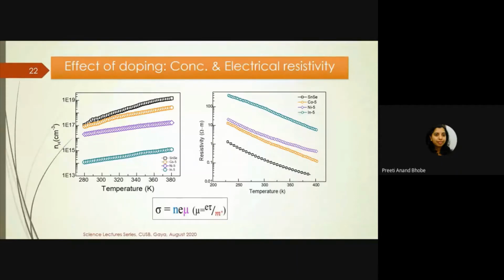What we find from the Hall effect studies is that the carrier concentration is getting affected to a large extent. In the case of the indium sample, you see the carrier concentration is really low compared to the black curve here, which is SnSe. Whereas with cobalt and nickel, the carrier concentration is also coming down, and this is challenging to our thought, because we were putting in metals and yet we are having a decrease in the carrier concentration. But otherwise, if we just look at the carrier concentration and resistivity alone without thinking too much, then we see that okay, carrier concentrations have gone down, so my resistivity has gone up. Nothing to challenge here.